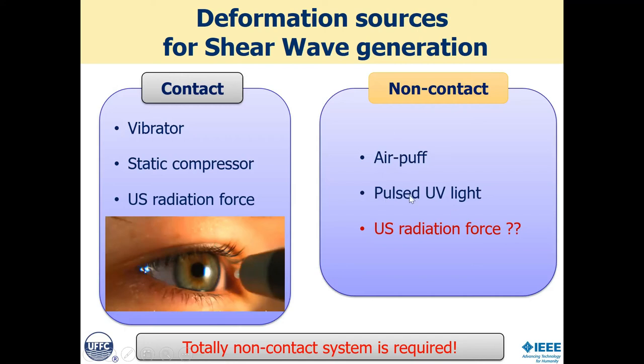For non-contact, there's the clinical tool called an air puff, which literally is that, a puff of air. It's very coarse and crude, so it does not produce high enough frequency mechanical waves that you can do robust imaging. We looked at using photoacoustics, because that's what we know how to do. So we looked at pulsed UV light that worked to launch waves, but was very inefficient and was probably going to be a safety risk if you tried to transfer it clinically.